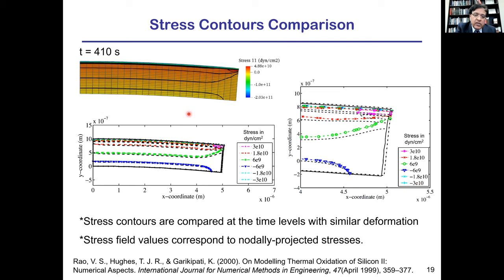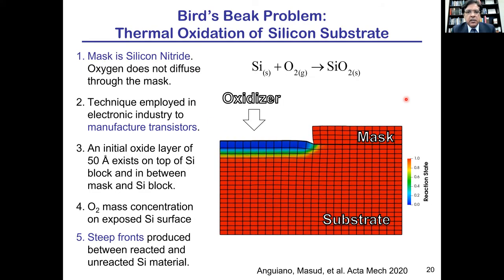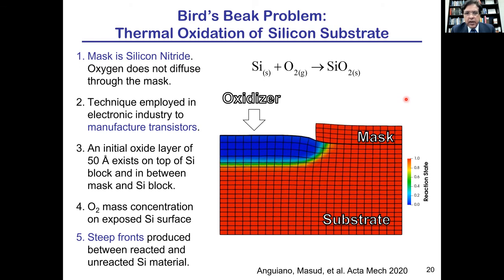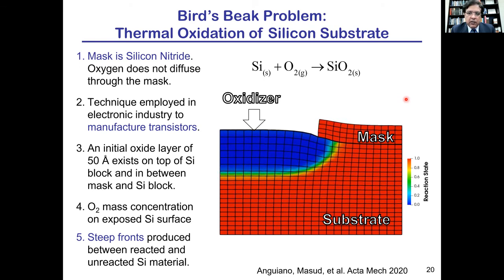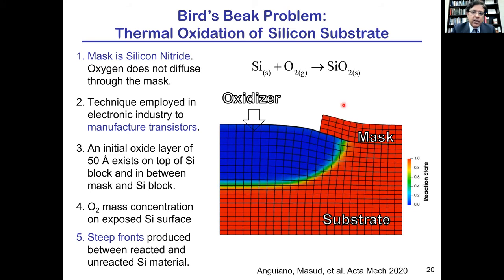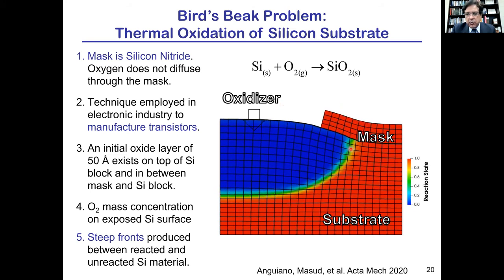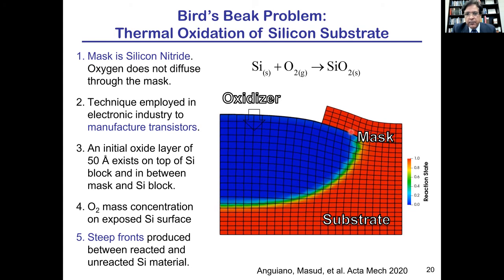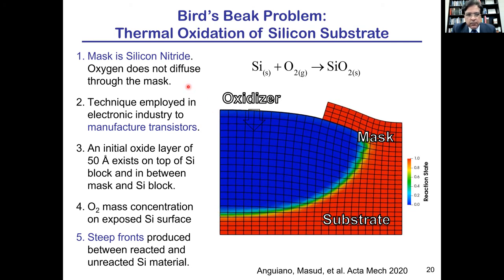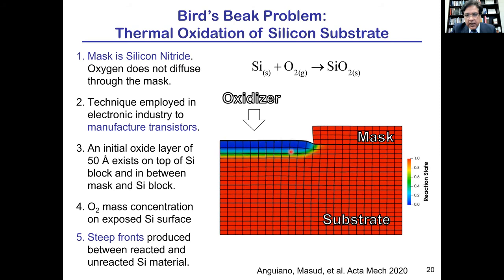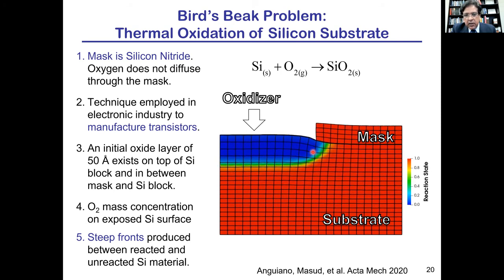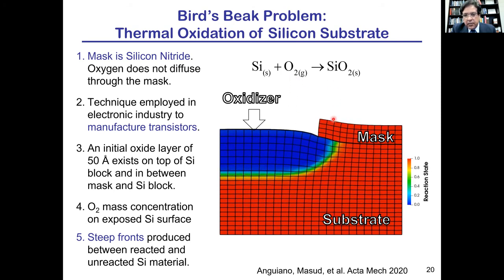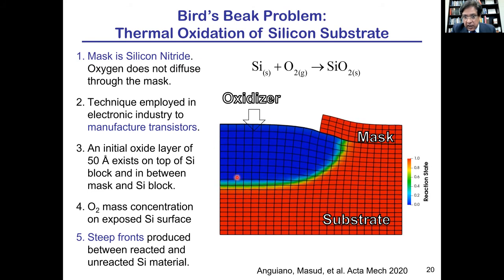We have plotted the stresses for this case and done a comparison with some published results in the literature for equivalent deformation. The next test case is the bird's beak problem. This is a typical problem in the electronics industry for manufacturing transistors. We have a silicon substrate, which is masked by silicon nitride, which is impervious to oxygen. As oxygen diffuses, the material front moves forward and silicon dioxide is produced, which is substantially larger in volume.